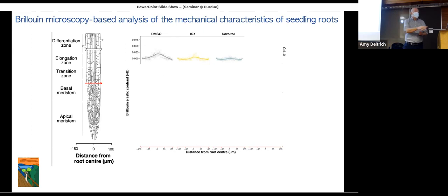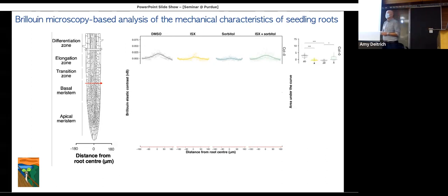Now, the interesting thing is, if you combine the treatments, you get stiffness levels which seem to be quite similar to the mock situation. This suggests it's a relative process, not an absolute exercise, and would also be in accordance with what we see when we give osmotic support to the isoxaben-treated seedlings, where we get the suppression of all the effects. So it looks like the cell wall is quite normal.